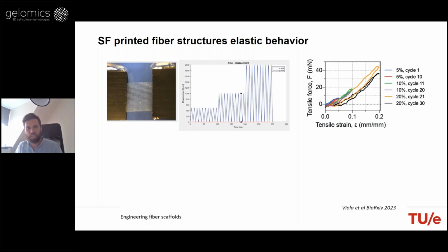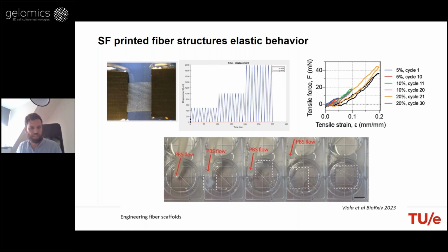told us that indeed the combination of electrowriting with the post-treatment with sodium phosphate seemed to induce a more elastic-like type of behavior that was confirmed by these mechanical tests. And this is possibly attributed to the beta sheet crystalline structure and organization of the printed constructs. We then also went further to basically, as I showed for the heart patches, that a possible delivery approach is to deliver this patch through minimally invasive surgery, so deliver them through a small catheter. We also explore the potential of these silk-based constructs for the same minimally invasive delivery strategy.